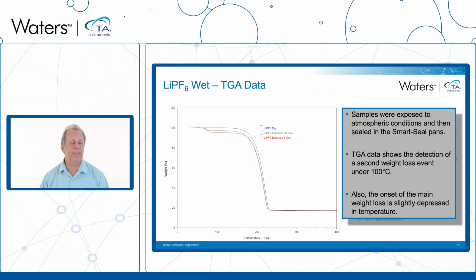Now, we compare this against a second example where we have taken 2 samples of LiPF6 powder and we've deliberately exposed them to atmospheric conditions of water vapor. One we exposed for 30 seconds and one we exposed for 5 seconds. So the 30-second sample somewhat mimics if you had a sealed TGA pan and you opened it prior to loading into the TGA furnace. The 5-second is obviously something where you are making as quick of a load into the TGA furnace as humanly possible.